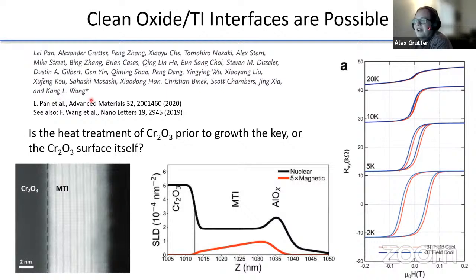And here I'm showing some excerpts from work we did with Kang Wang's group at UCLA. And one of the interesting things here is that this actually involved an ex situ transfer. So the chromia was grown in this case by Christian Binek's group and then sent all the way to UCLA, where the topological insulator was grown on top. But chromia is phenomenally stable. And what they did was a really high temperature heat treatment in vacuum prior to growth. So this may or may not actually be the key to getting this sort of higher quality interface.